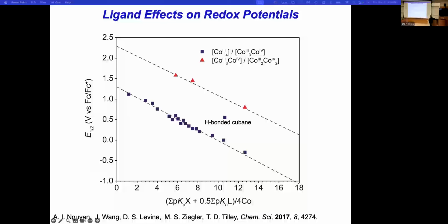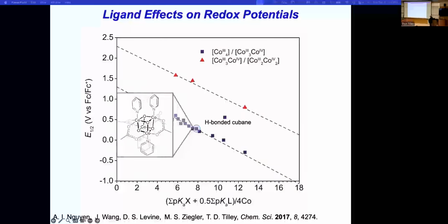But in between, you have one of the cases where there's a hydrogen bond to one of the bridging oxos. This is a potential that's displaced by about half a volt from the lower line. And it's about the same potential you'll get if you just put that species in water. So there's undoubtedly water hydrogen bonding to the oxos in solution. Okay, that's the parent system right there.